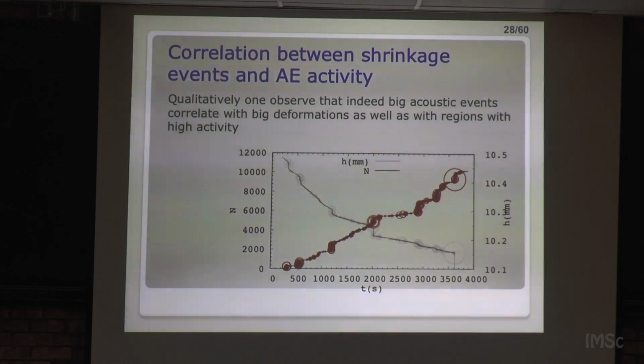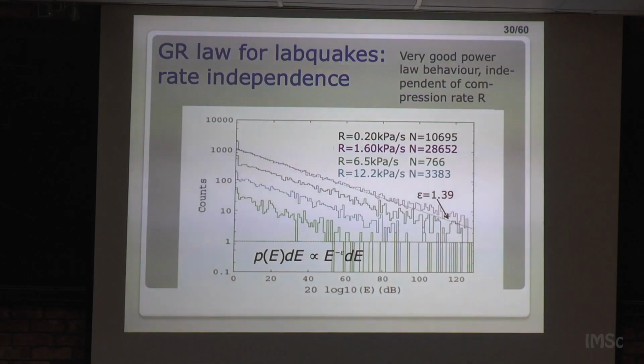Okay, well, you can also see here again the cumulative number of events and how the height of the sample is decreasing, and these circles show a size proportional to the log of the energy of the event. So you see that these big failures are usually generated by a big event. There's a big event that generates this sequence of aftershocks, okay? Okay, so, well, I can skip this one.